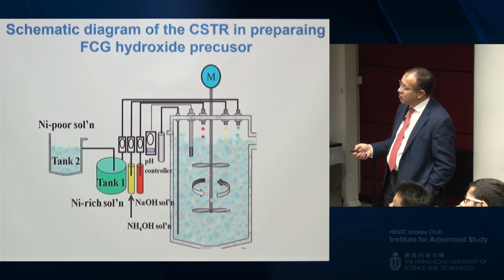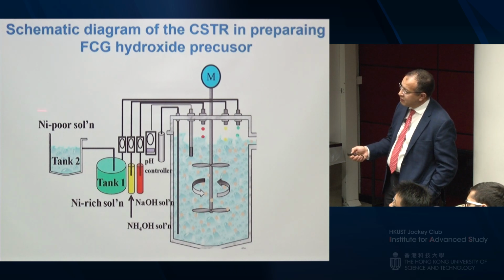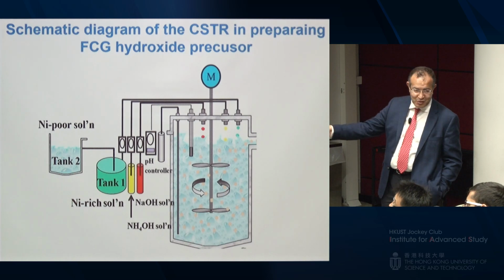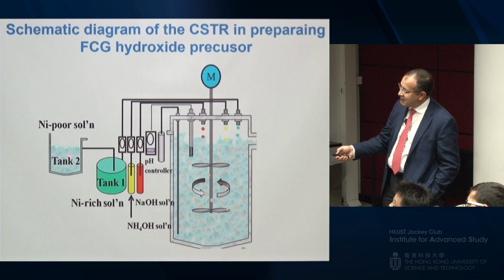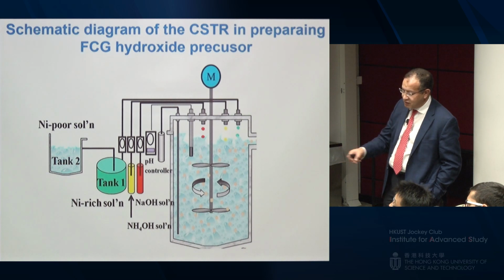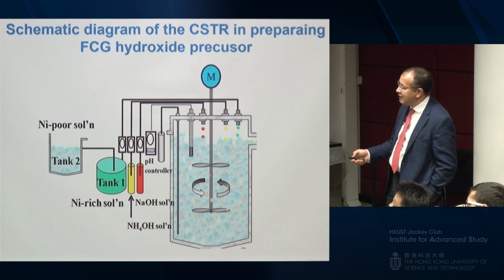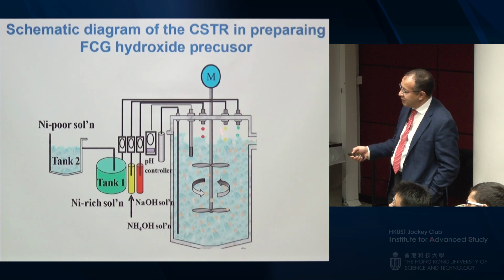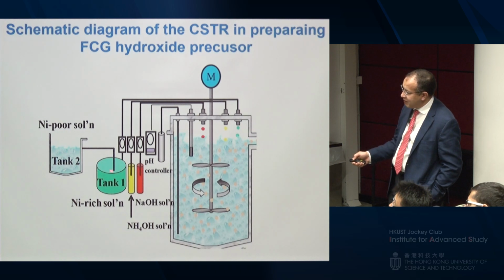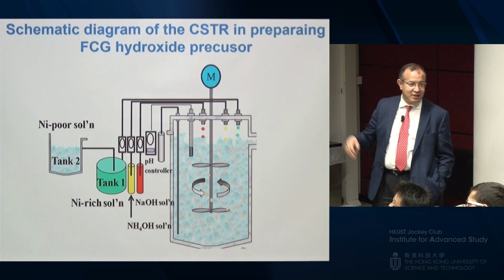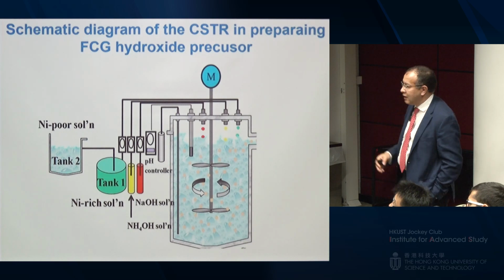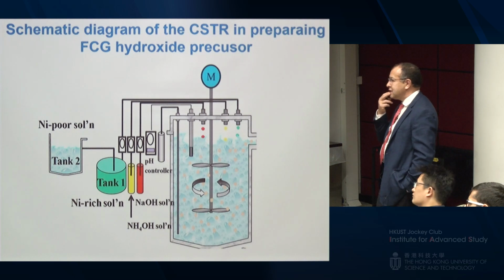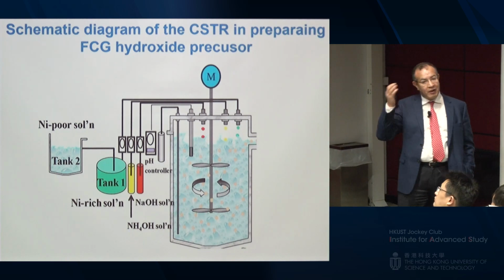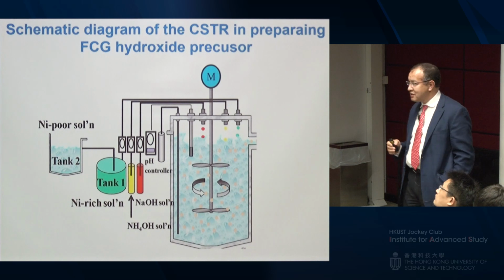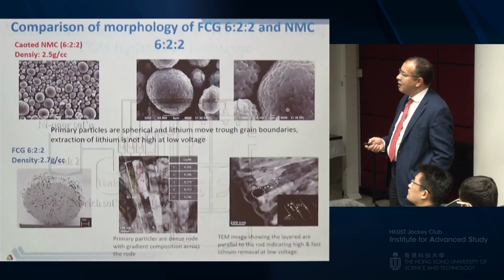With this new approach, you just add one more tank. That's your investment. One tank that has nickel rich, so you can put the nickel first in the bulk, and then one tank that has manganese rich. Cobalt can be the same composition if you want to keep it constant across the particle. Then once you start moving the nickel to the reactor, you dilute the nickel with manganese and cobalt both. With time, you're changing the composition. So one company that licensed it has already scaled up this material to 10 tons a day. So there is some serious work going on now.